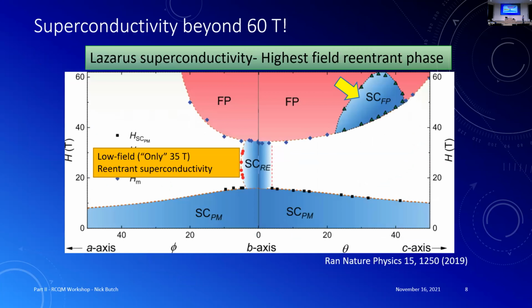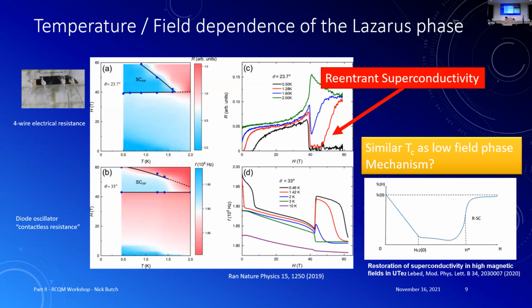All right, and so if one then does a whole bunch more experiments and asks what's going on at high field, this is the field angle here. This is effectively a zero temperature phase diagram, with magnetic field here. So along the B axis, there is this superconductivity. It's limited to a fairly narrow range of angle. It ends here at 35, where FP means field polarized, but there's a metamagnetic transition here. And as you go towards A, it's got this curvature, and you go from B to C, it goes this way. But then surprise, there's a pocket of superconductivity on the other side at higher fields. That was dubbed the Lazarus phase by the fine people at the Mag Lab, and I like that name. So it's reentrant, it comes back from the dead. So there it is. If we want to talk a little bit about the properties of the Lazarus phase.